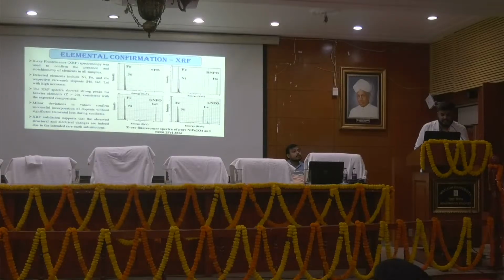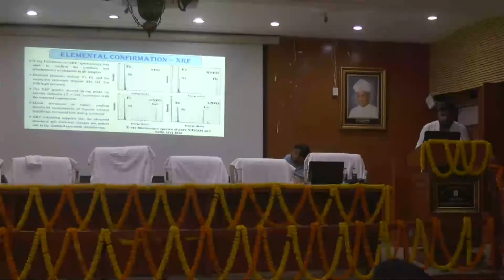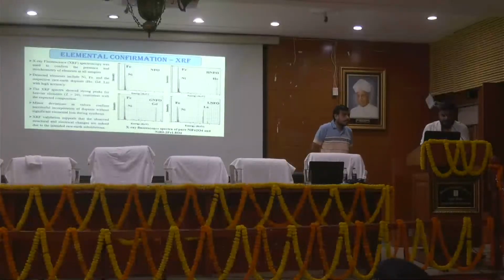And this is the XRF elemental confirmation. We have performed the XRF to confirm that the rare earth dopants are uniformly segregated in the sample, and that's why in the first figure you can see that there is no additional phase.